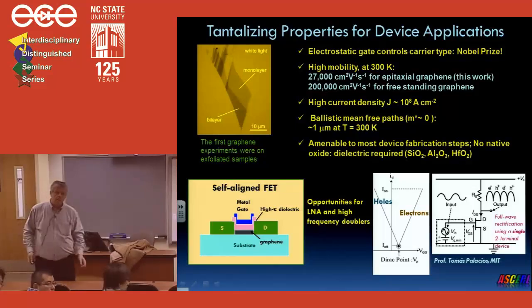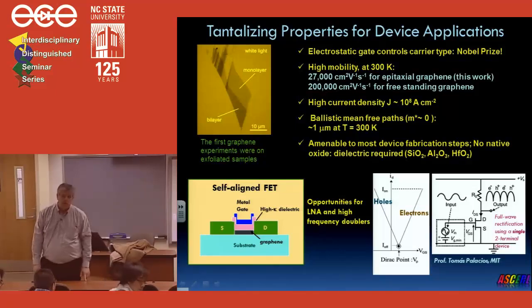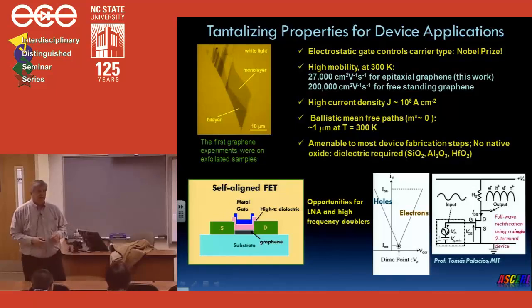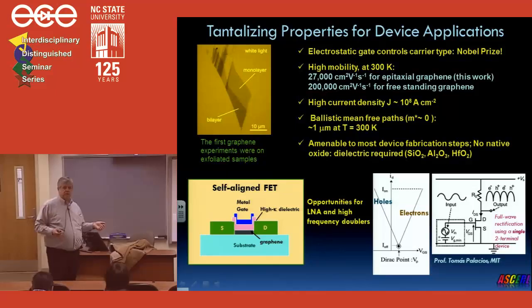Effective mass very negligible, does it mean very low resistance, or what does that mean? Well, it means that the carriers act as if they have no mass, so they can accelerate to their saturation velocity under a very weak electric field extremely quickly. And that becomes valuable for device technology. I don't know the figures offhand, but for gallium arsenide, the saturation field is what, 10 or 20 kilovolts per centimeter? Whereas for graphene, it could be like 1 kilovolt per centimeter.